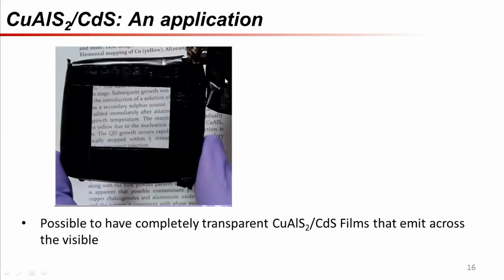What I'll add here is that there's a slight trick here, and I'll admit to it, which is that when we say copper aluminum sulfide, we mean a structure which has copper, aluminum, and sulfur in it, but invariably in nanocrystals, the stoichiometric ratios of copper, aluminum, and sulfur are seldom exact, and this is a very well-known thing. So when you're making a nanocrystal, the exact chemical formula will be slightly different from CuAlS2. It will differ. In fact, we find wide variations there depending on the size of the nanoparticle and the ligands which are used.